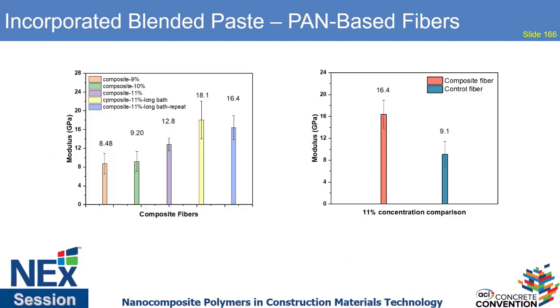So if I look at the next slide here, what this is showing is a comparison of a controlled polyacrylonitrile fiber where we're starting to do this and a composite. And you can see an 80% increase, and the amount of nanomaterial is just coming from that paste. We're also increasing the amount of polymer here, and the reason we're doing that is we need to find the sweet spot to spin these. So we're looking at the non-Newtonian filament stability process.